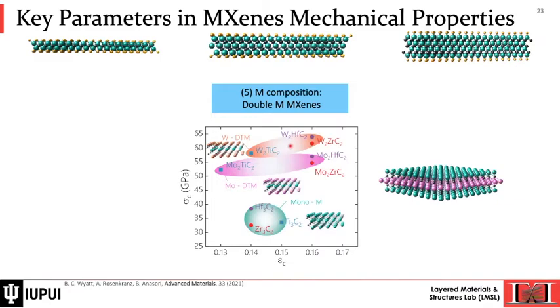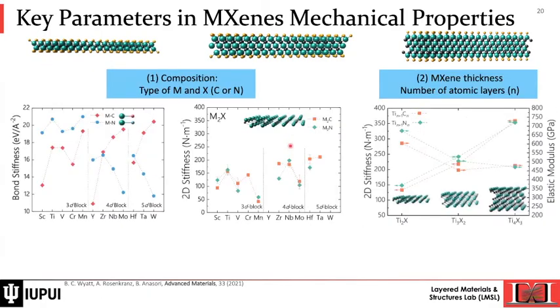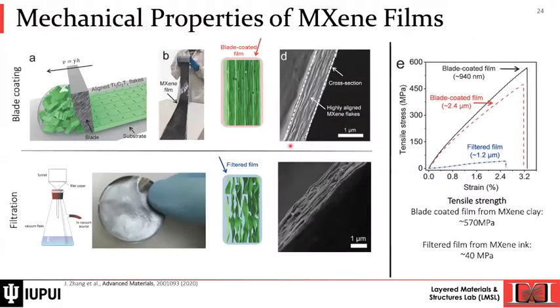Now, these are about a single flake of MXene. You might say, well, single flake is nice, but we work with large quantity of MXene. We make a film. For making the film, all of these variables that I mentioned from 1, 2, 3, 4 apply. Plus, it also depended on how you prepare your MXene film or MXene structure, because these are individual flakes. But if you work in the larger scale, which is usually the level that we need to, we're not working with the 1 nanometer flake only, we have a stack of these flakes. Then we talk about how we order these layers together.